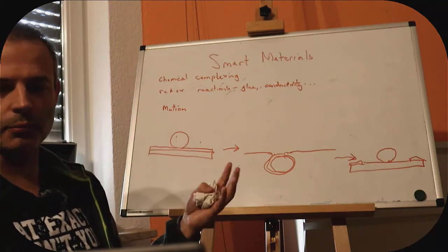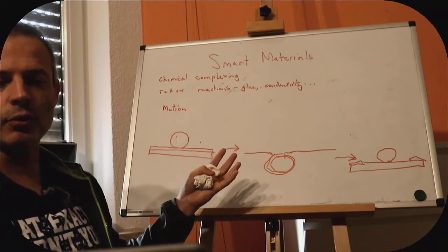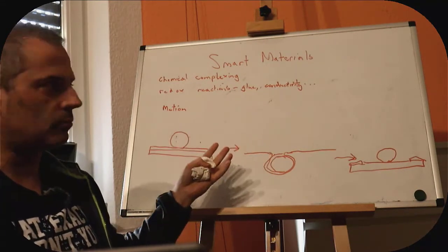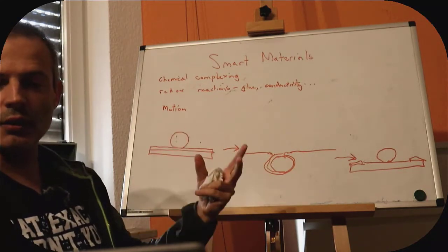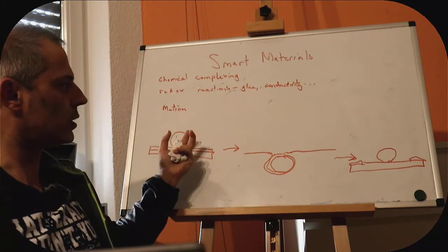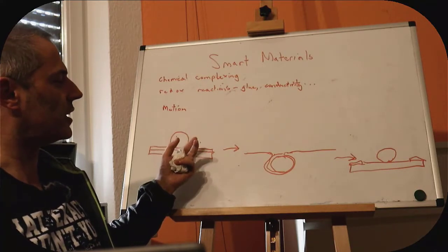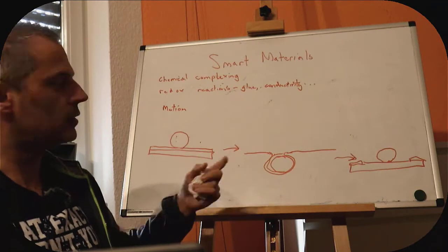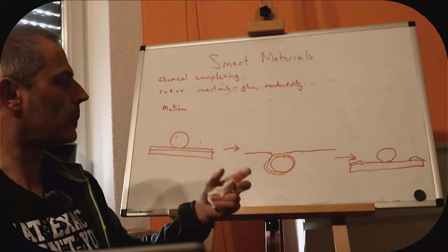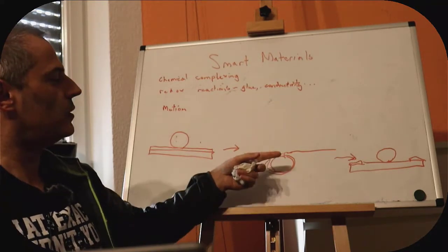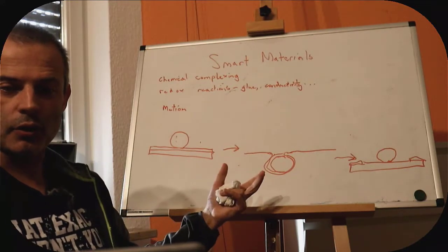Some research groups use a similar method, wetting and drying, to form boxes and shapes, which are caused by the drying of a liquid drop typically. So as the drop dries, it evaporates. Obviously we wouldn't do that with mercury. It evaporates, and that changes the size, and eventually it leaves. And if it manages to get two sides to attach, then usually they stay. And if we can get the drop out without it all collapsing, without it crushing the whole structure, then we end up with a hollow structure.